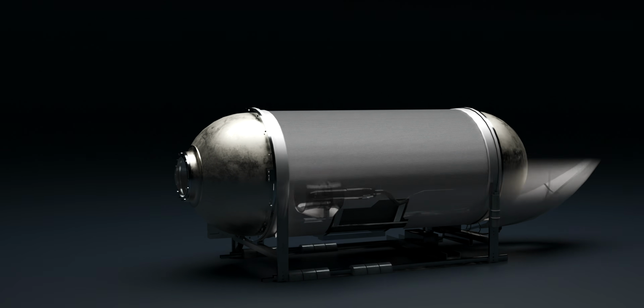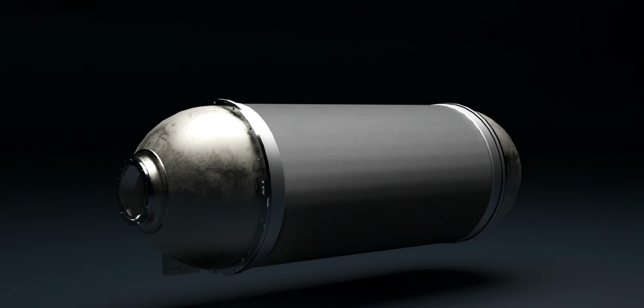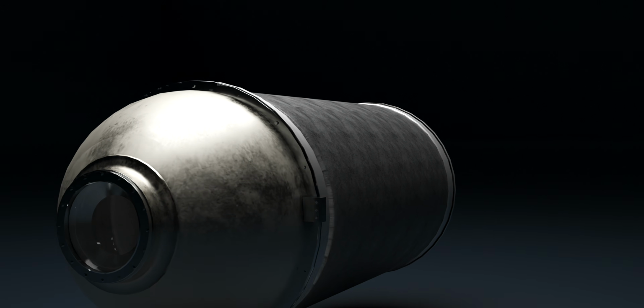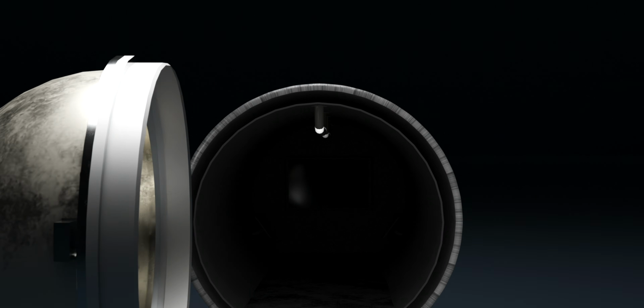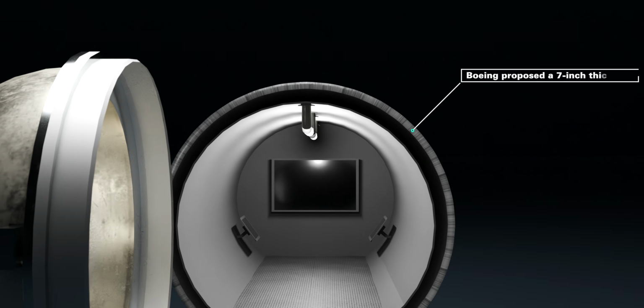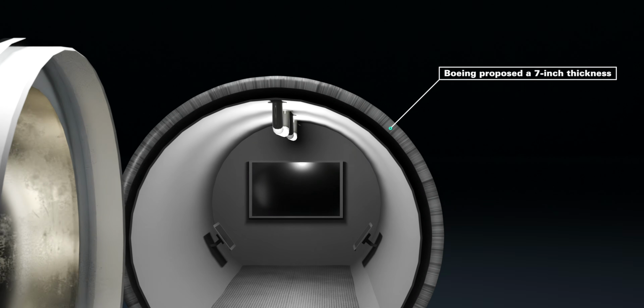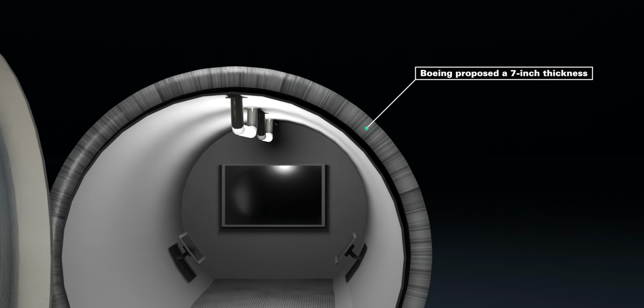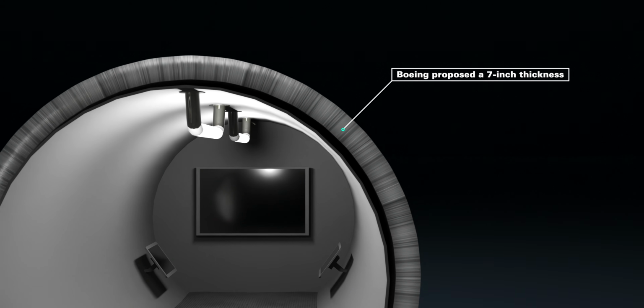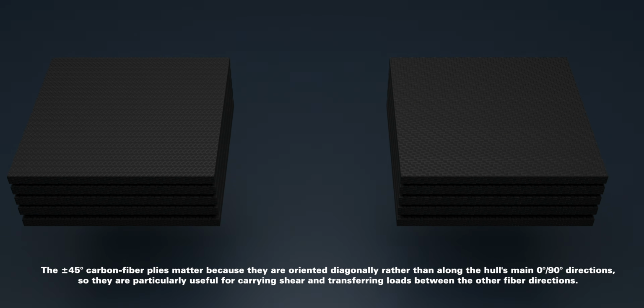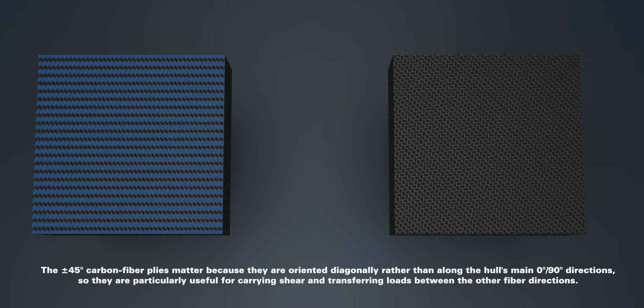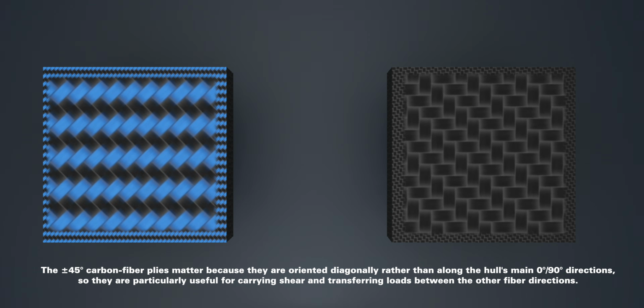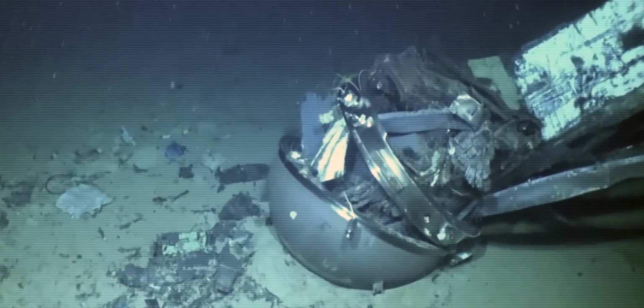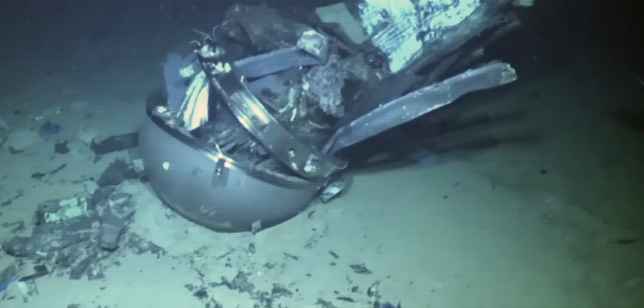Perhaps most significantly, the completed pressure hull no longer matched the original design. An early feasibility study by Boeing proposed a wall thickness of approximately 7 inches. Titan's production hull measured only 5 inches. The final design also omitted the plus 45-degree carbon fiber plies originally proposed to resist shear stresses within the laminate. When investigators asked why these changes had been made, no documented engineering justification could be produced, and Boeing had not been consulted after its initial feasibility assessment.